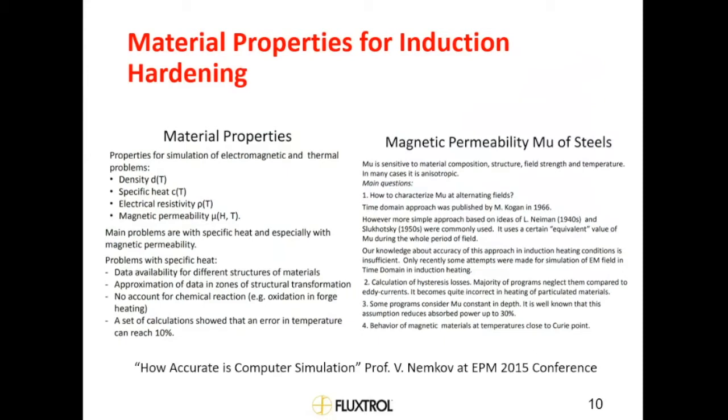So now we need to start thinking about those phase transformations, which are primarily what's driving a lot of these differences in the specific heat capacity. It also affects the resistivity and the magnetic permeability. So these differences really should also be time dependent, and dependent on the incoming structure. These are things we're still working on.